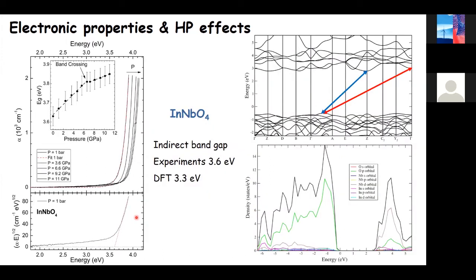If you go to indium niobate, we have seen similar results. You can see here, this is oxygen dominated, and I have niobium dominating the states in the conduction band. This is indirect, and this is an important fact. We have 2 indirect band gaps at ambient pressure.